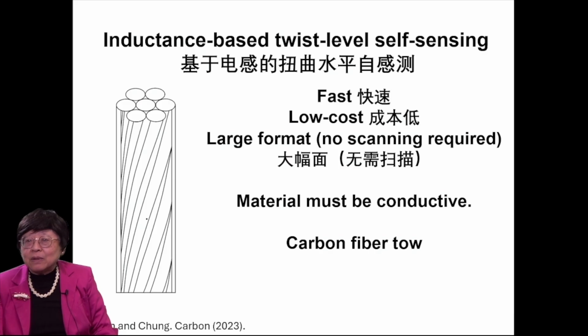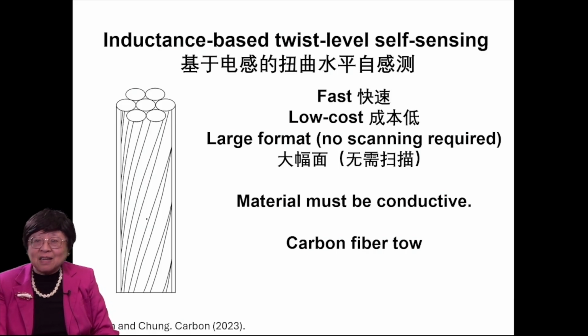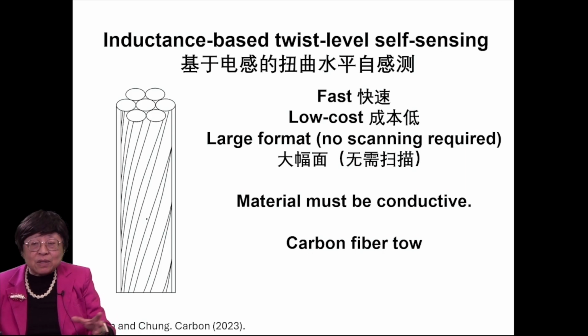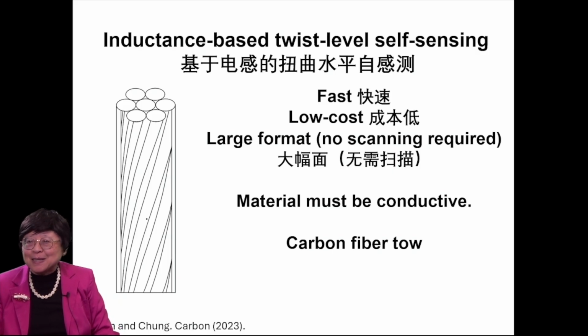And we discovered that the twist level, how much twisting, we can tell by inductance measurement. This method of twist level self-sensing by inductance measurement is fast, low cost, and large format. No scanning required. The long tow, you can measure the inductance, and from that tell the twist level.